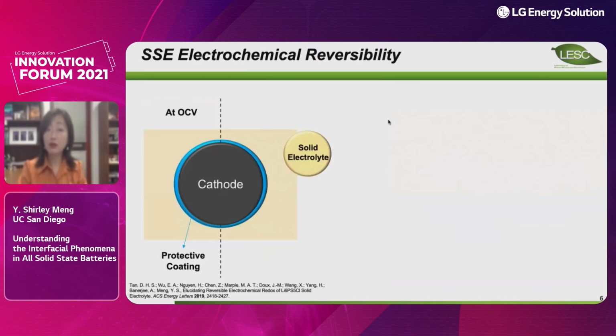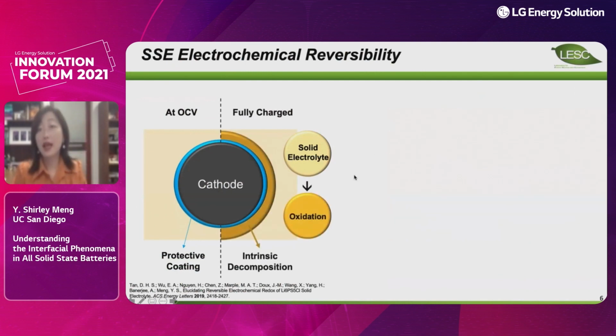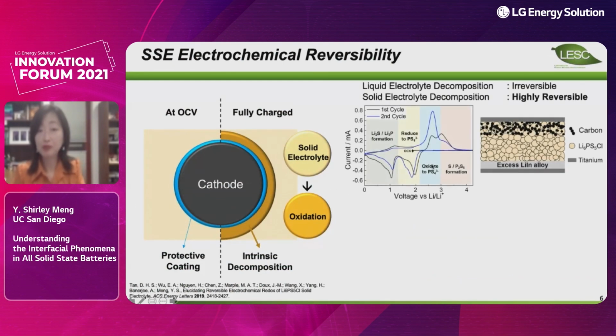Once we solve the chemical stability, the next thing we need to worry about is the electrochemical stability. The sulfide electrolyte has a huge challenge because it has a very narrow electrochemical window. So as Professor Linda Nazar already showed, if you put a lot of carbon in your solid electrolyte, you make a pseudo battery like this to basically use the solid electrolyte as your cathode. You can observe nice redox peaks from the oxidation of the solid electrolyte.